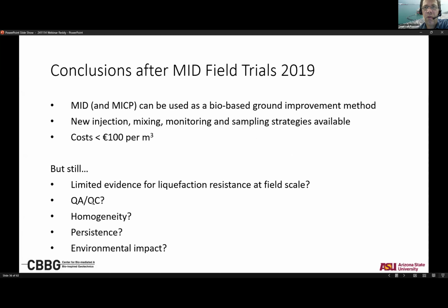Quality assessment, quality control methods: we don't yet know how to assess the quality. Pressure wave velocity is one way, but it can only test relatively locally where the gas is situated, and doesn't really show at a small scale where it is. So it will also not show how the gas is distributed at the pore scale.